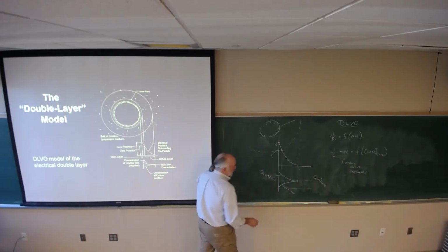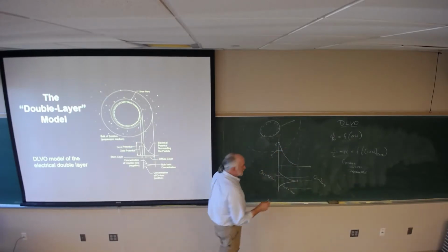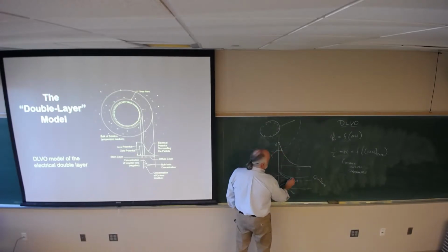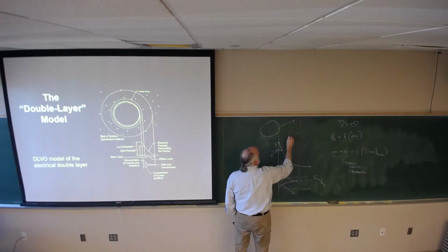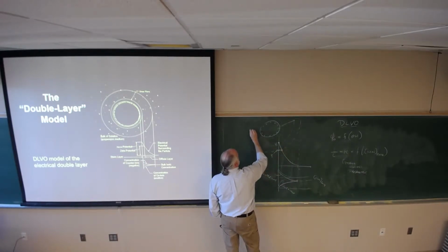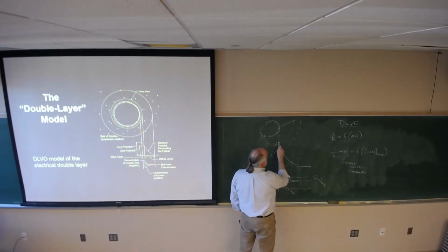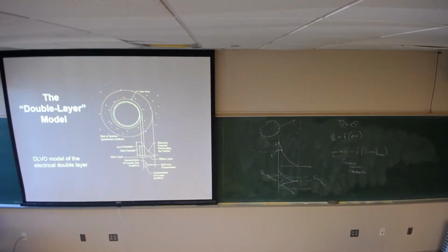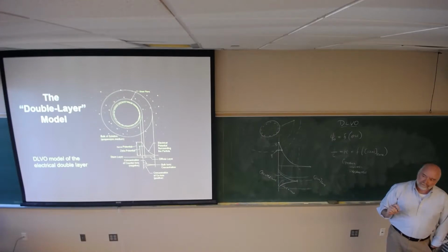So let's do that. I increase the concentration of ions in solution, and I'll draw it now in blue. I see then the decay function gets faster. My double layer thickness then does this. Good. So what happens to my Nernst potential? What happens to the Nernst potential? Nothing. Good. Why not? Because we're not affecting the Nernst potential by changing the ions.